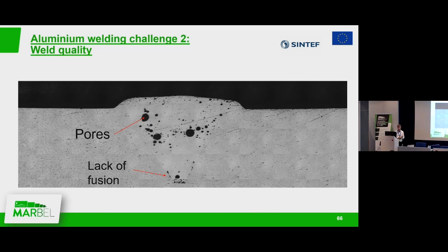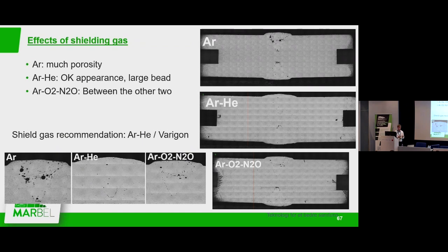But we have other challenges with aluminium welding. Aluminium is more susceptible to pores, and we have challenges with lack of fusion in most cases, where we try to apply as little heat as possible. So here we do a lot of experiments, try different welding procedures, and also try different shielding gases. The shielding gas creates different welding processes, narrows the arc and creates a deeper penetration depending on what shielding gas we have. We have chosen and tested different ones and found that an argon-helium mixture with a little bit of hydrogen, Varigon for instance, is excellent for deep penetration and low porosities. So then we have full penetration, low heat, and no pores.